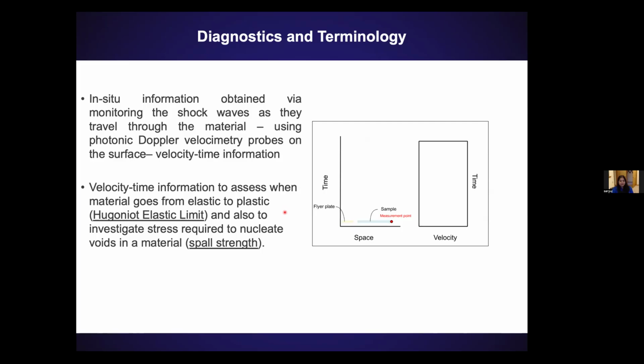So I'm going to run through an animation on the right side here, where you're going to see that space-time plot that I showed you, and what that might look like in the velocity time space. You get impact, and here's your laser point, by the way, the PDV point that you're measuring at the back surface of the sample. As the sample gets impacted, the shock hasn't reached the back surface yet, so essentially, your velocity is zero. The back surface hasn't caught anything. When, if your material